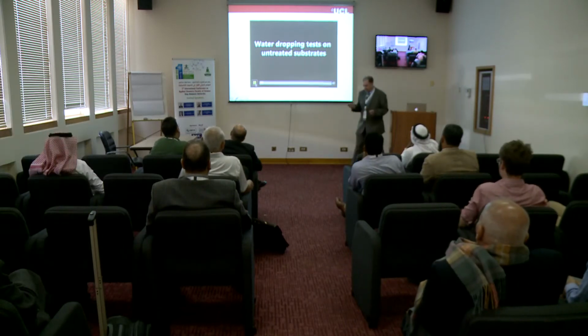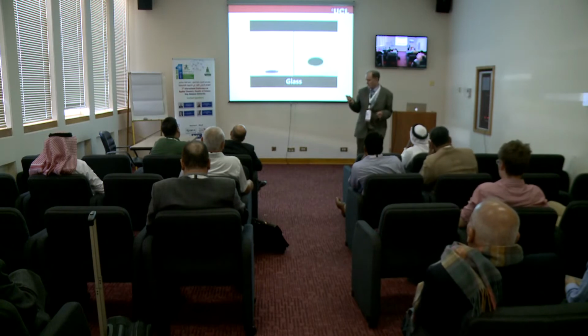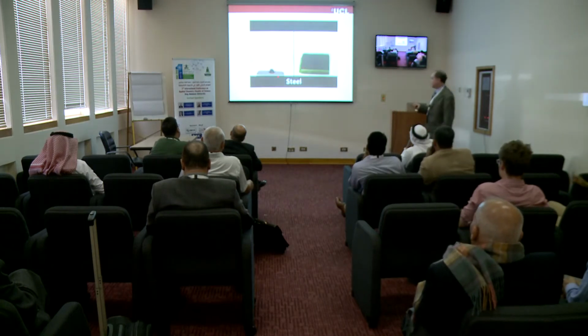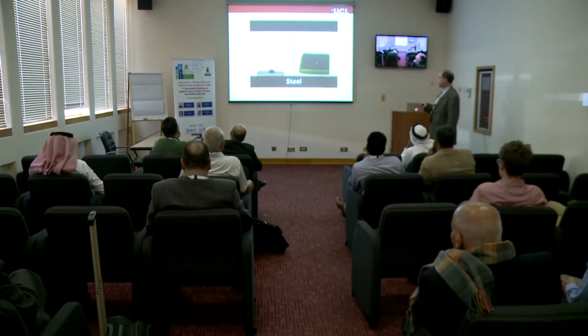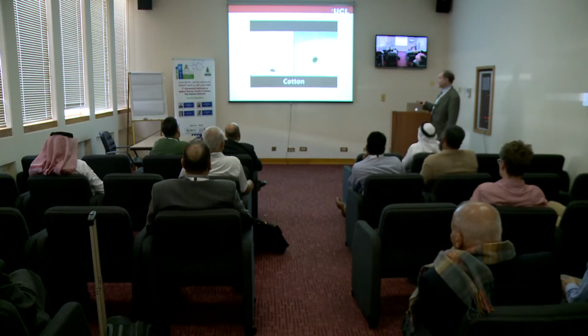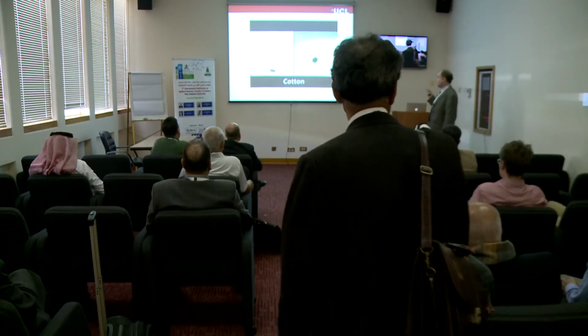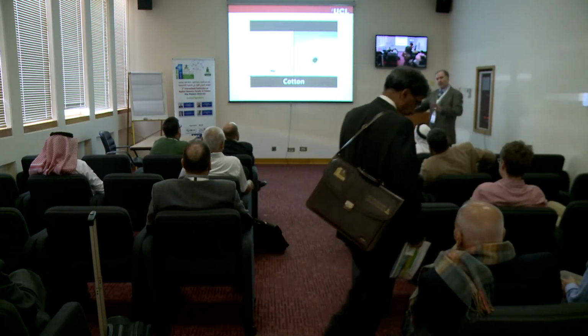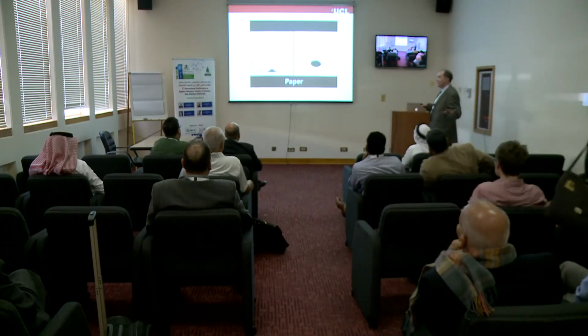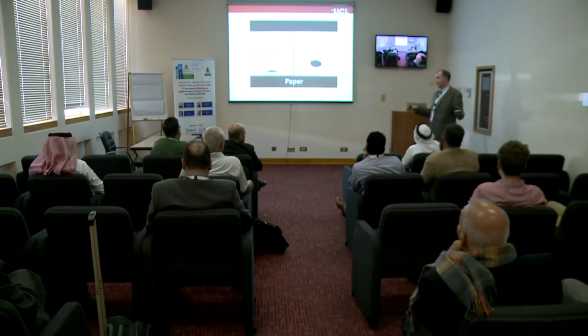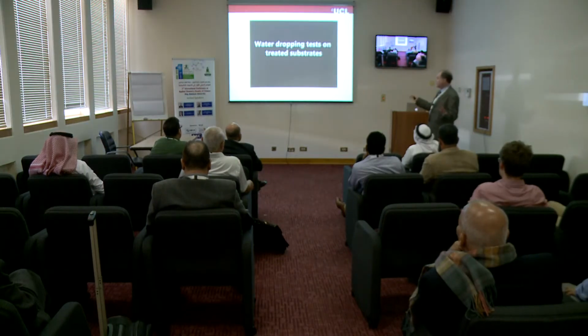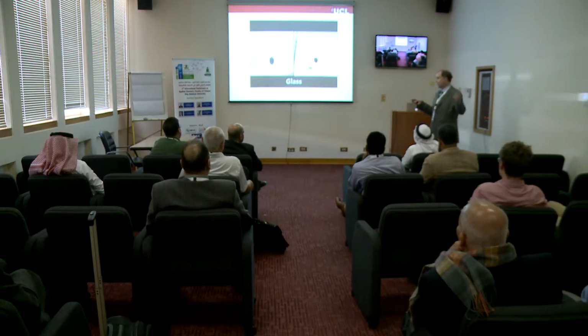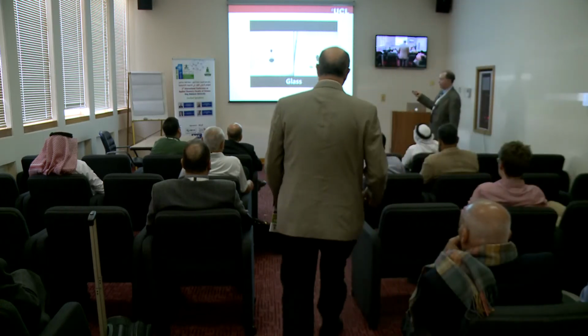And these are further examples. First of all, this shows you what it looks like on an untreated material, for glass, for steel. I think we're going to have some paper coming in, and cotton. So cotton, if you just drop water on there, it just absorbs into the surface. With our treatment, we can coat virtually any surface now with our super hydrophobic coating. This is work which we published in Science earlier this year. When we do that, the water gets repelled from those surfaces and just bounces off. So that's what happens on glass.